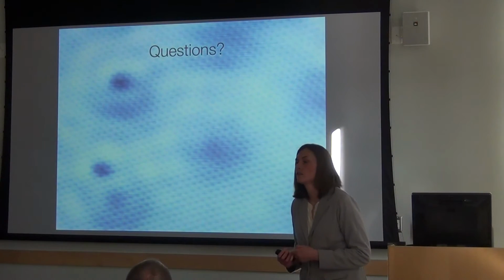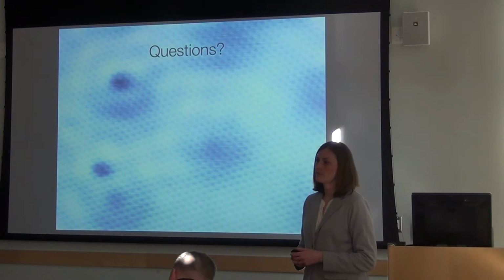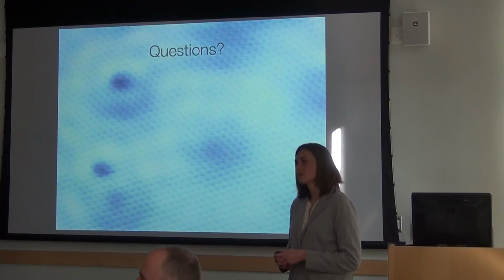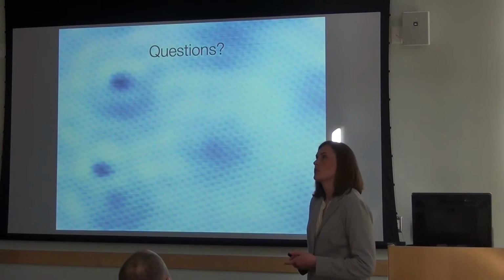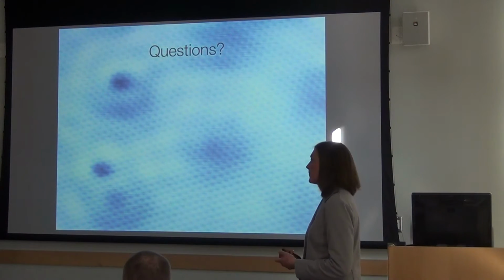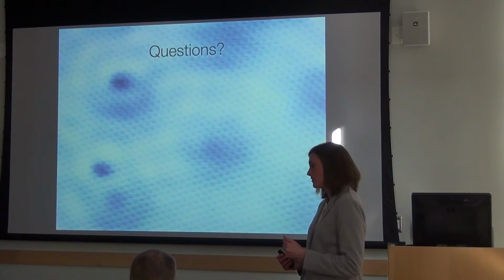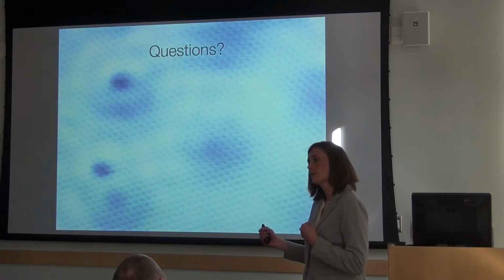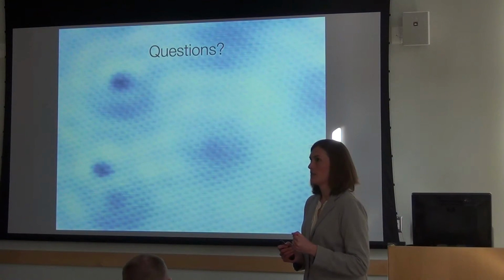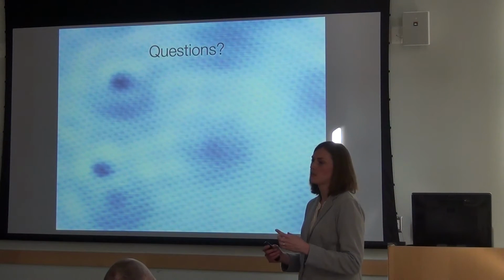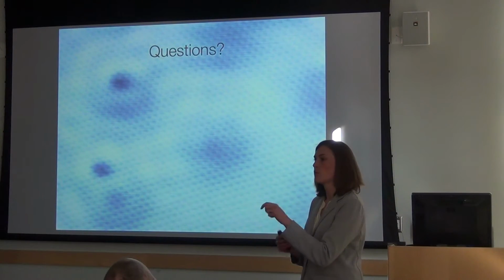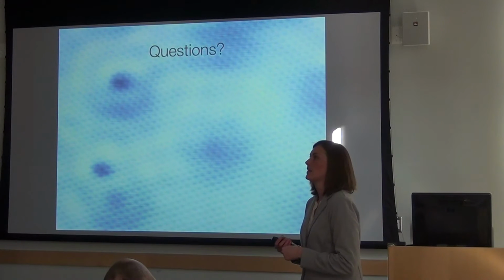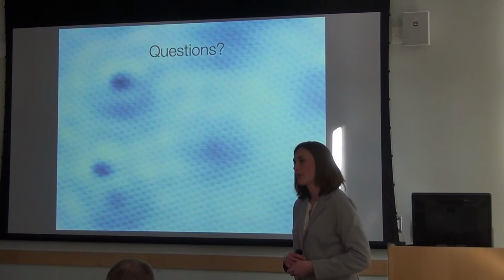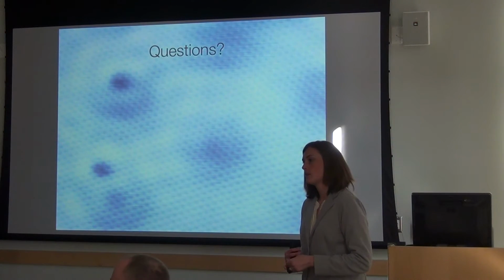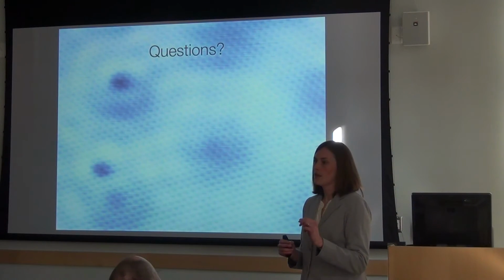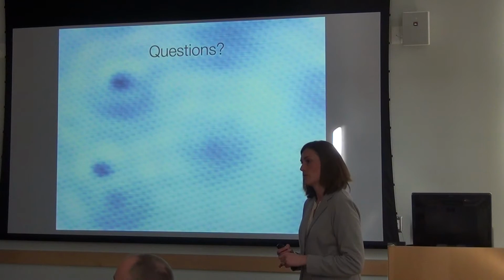You said your method had more order than previous methods. I mean, as I understand, this is a layer of atoms on which you're putting another layer. How is this disorder versus order defined? So what is the disorder in other experiments? Is that the question? So they were able to show that the hydrogen atoms adsorbed at preferential distances from each other, but this was an STM experiment, and there was no other, so it'd basically be a ring if you did an FFT. You wouldn't see points, you would see a ring. So that shows some order, but it's not a crystalline order. I'm not sure if that really answers your question. It's randomly distributed on the surface at some preferred distance is what people have seen previously.